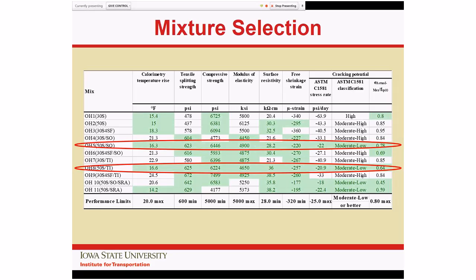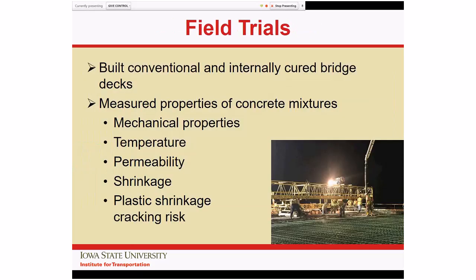with internal curing. Now, the shrinkage-reducing admixtures, again, did really well in the shrinkage parameters, but they did hammer the setting time and the strength development. Silica fume systems did really well from a permeability point of view, but did not do so well from a shrinkage point of view. So based on that, we seem to have settled out on a system that we could move forward and recommend to the DOT: a 50% slag, lightweight fine aggregate system would seem to provide a really good way to go.